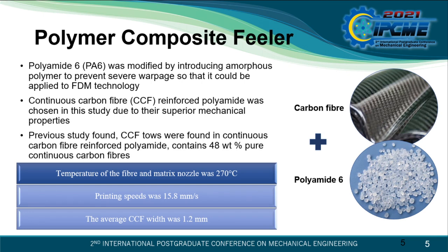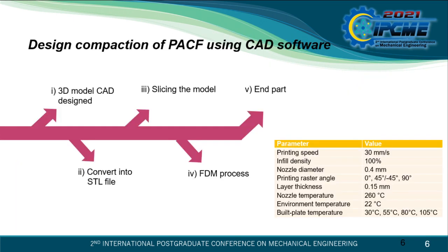In a previous study, continuous carbon fiber reinforced polyamide, which is CFRP, was found to contain 48 percent pure continuous carbon fiber. This material used parameters which can give good properties in the end part: the temperature of the fiber and matrix nozzle was 270 degrees Celsius, the printing speed was 15.8 mm per second, and the average CCF width was 1.2 mm. 3D printing uses CAD software to design the compaction in PACF.